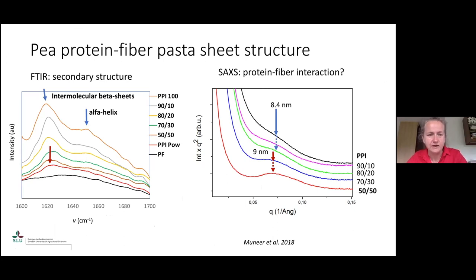So this information can help us understand what is happening in the microstructure, and in the secondary structure using the FTIR method. It shows that if you have only proteins, we have a domination of intermolecular beta sheet structure formation versus alpha helix. This goes on for all of these, this is in proteins, this is in the blends. And then we have only fiber, where no such secondary structures are present. So it's additional information to understand the system, and it's rather helpful. Although for the SAXS part, I still put a question mark.